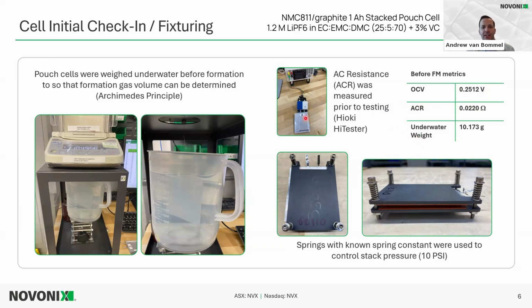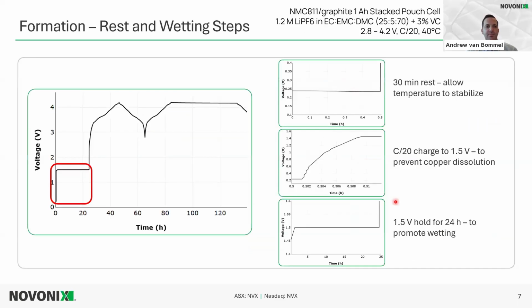After that check-in, the cells are placed between two plates. These have springs with known spring constants so that we could fixture the cells to a standard stack pressure. There's rubber pads between those plates to even out the stack pressure. And these are controlled to 10 psi for our normal NMC graphite cell, for example. So that's how the cell is checked in.